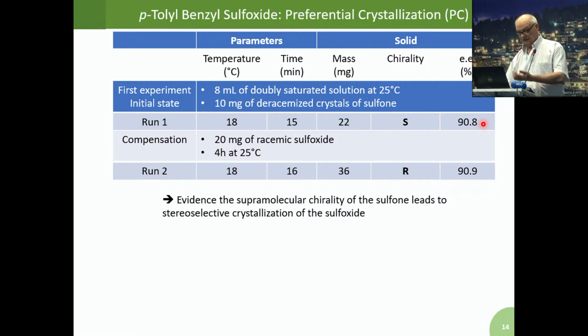Then starting from this solution, now we get an excess of R inside, and indeed, at the second run, we obtain the R enantiomer. So we had the clear evidence here that starting from a molecule which is not chiral, but crystallizing in a chiral space group, we can initiate a preferential crystallization on a chiral molecule.